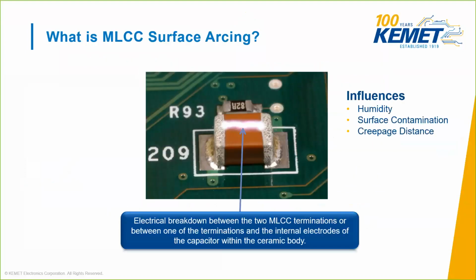All right, so one of the primary concerns when operating these capacitors at high voltages is the risk of arcing in the application. Surface arcing is the electrical breakdown between the two MLCC terminations or between one of the terminations and the internal electrodes of the capacitor within the ceramic body. It occurs most frequently in applications above, say, 300 volts and is heavily influenced by humidity, surface contamination, and where there's minimal separation between the two termination surfaces. This is also referred to as the creepage distance. This phenomenon can either damage surrounding components or lead to a breakdown of the MLCC dielectric, resulting in a short circuit condition and catastrophic failure.